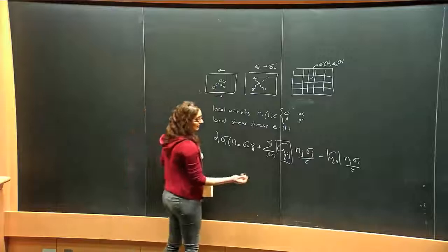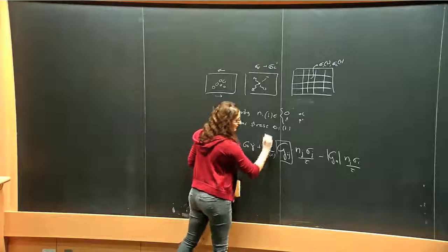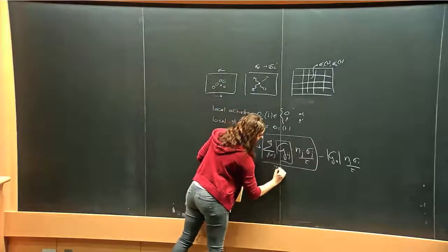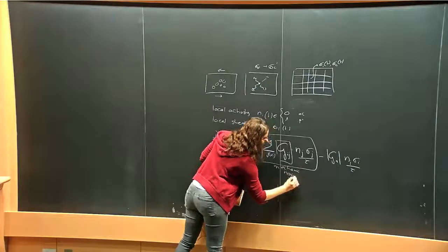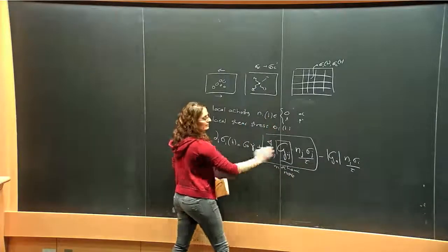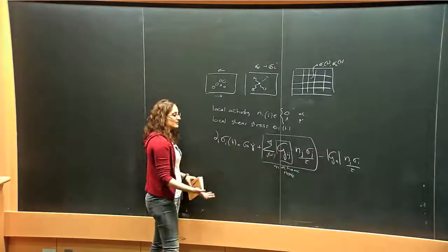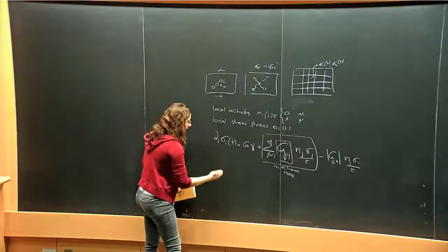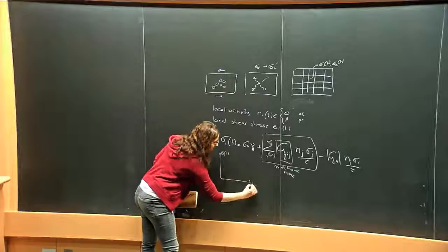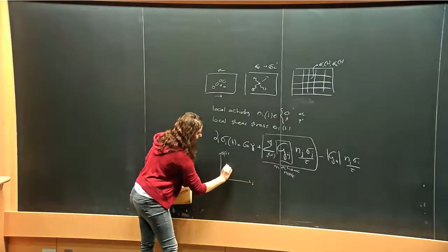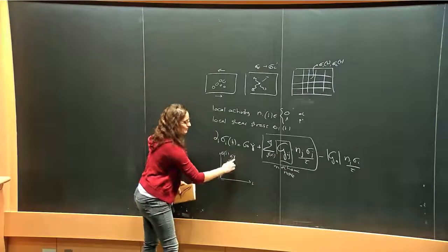And more importantly, I think also, is that once you have this equation, so you say here is the mechanical noise, it tells you how the plastic activity in your system will add fluctuation on the stress. You have here the local relaxation. But all the physics will be hidden in how your site becomes plastic to elastic. And so typically, you can assume, for instance, that if you look at the stress on one site, you will have fluctuation of the stress. So that will be given by the external driving.